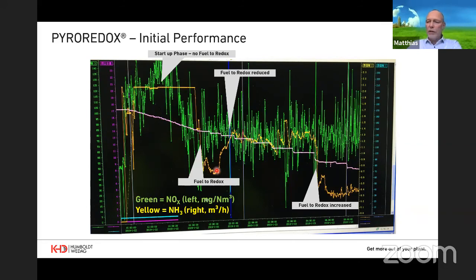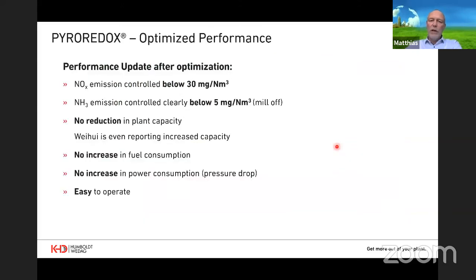Now we put the Pyro Redox into action by shifting fuel to the redox loop, and accordingly we can reduce the NH3 injection, and still the NOx emission is decreased. And this could be improved further on. We put more fuel to the Pyro Redox, and we could reduce the ammonia injection significantly, as you see, while still the NOx emission was low. But this was only an initial commissioning.